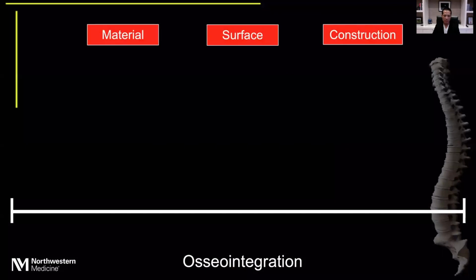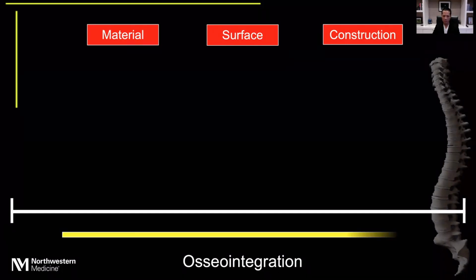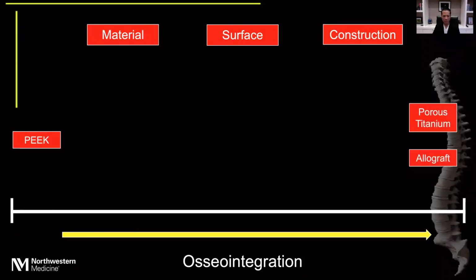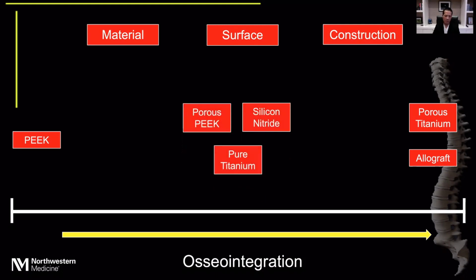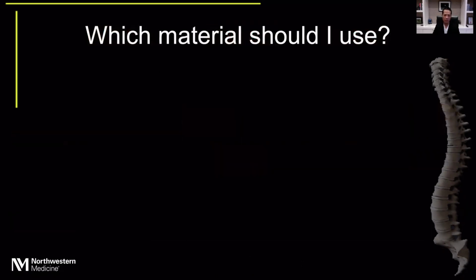When it comes to osseointegration, again, to reiterate, it's important not only for the material that you use, but also the surface in which it has been created and the construction of the actual device. On one end, the least amount of osseointegration can be seen with PEEK, and this is supported by the evidence-based literature. And on the opposite end, the greatest amount of integration can be seen likely with porous titanium allograft. Porous PEEK, silicon nitride, and pure titanium all probably lie within the center in some way, shape, or form. And one could argue what the actual relative performance is to each.